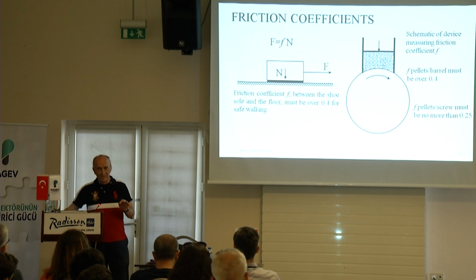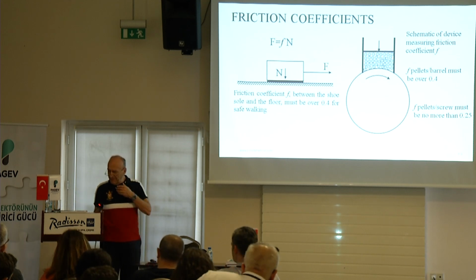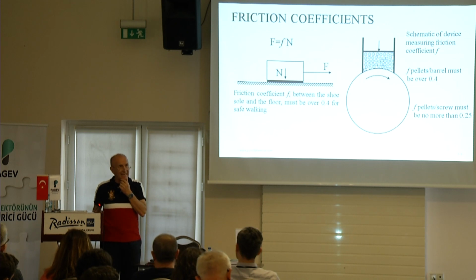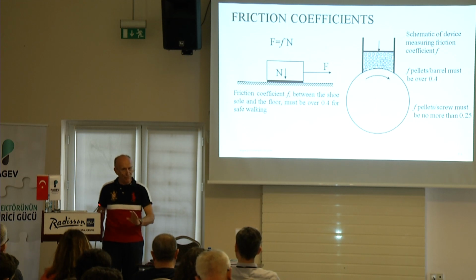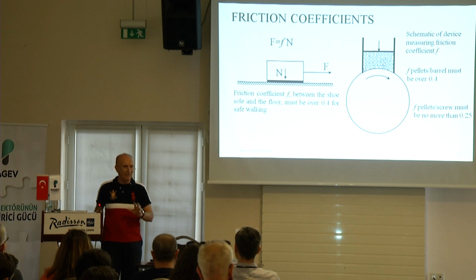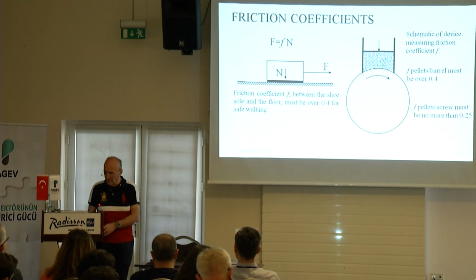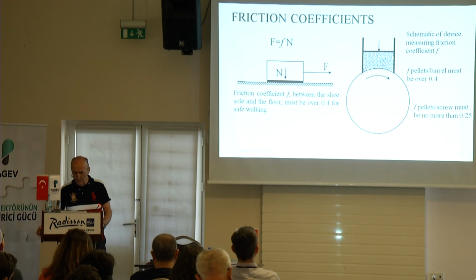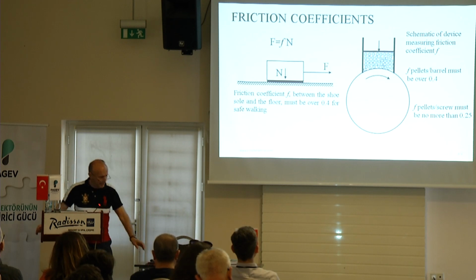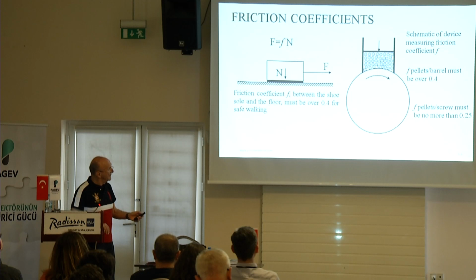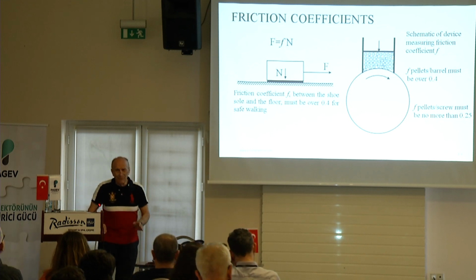Well, on the barrel, the friction coefficient should be at least 0.4. On the screw, it must be shiny, with a low friction coefficient of about 0.25, all right? So these are the ranges of friction coefficients that we like to have, as I have over there. On the barrel, we like to have a coefficient of 0.4, and on the screw about 0.25. So these are default values.